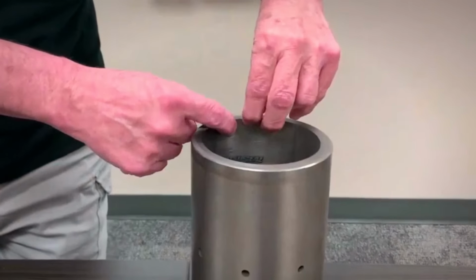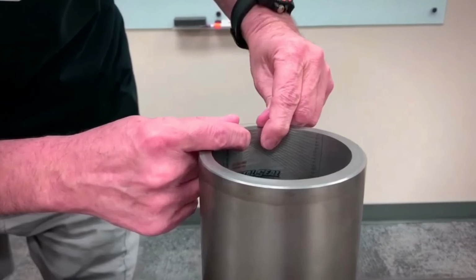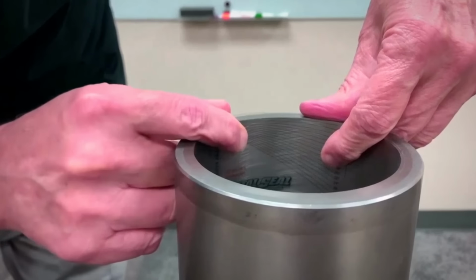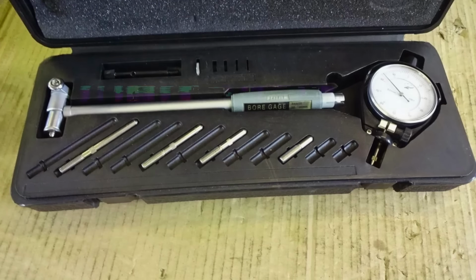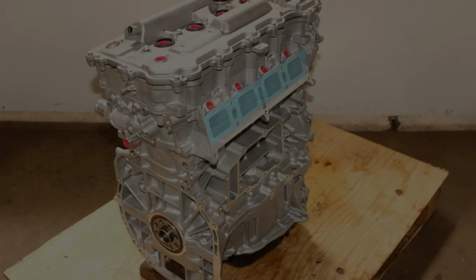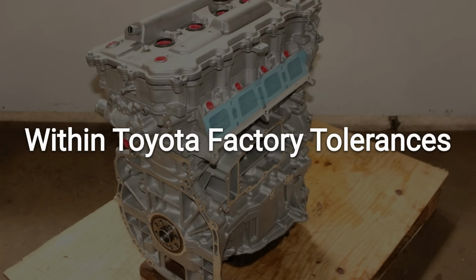But the actual bore diameter measurements, the number that tells you if the cylinder has actually worn oversized, were within 0.005 of an inch of each other. Statistically, that's close to the margin of measurement error on a standard bore gauge. In plain terms, both engines were still well within Toyota's factory tolerance for cylinder wear at this mileage, synthetic or not.